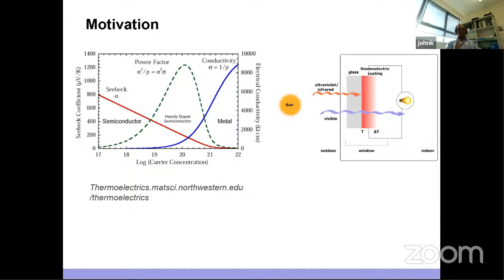So you are in between the region where you can have a high power factor, which can be done by doping. So it's quite good to play around with a very tiny amount of doping, or tiny ways of tuning the electrical conductivity and Seebeck coefficient. We may be able to have a significant power factor. So this is the area we concentrated on more, rather than looking at thermal conductivity tuning, which has been done a lot in the past. You can see on the right side a schematic diagram of how we envisage this being realized in a few years' time as a smart energy product.